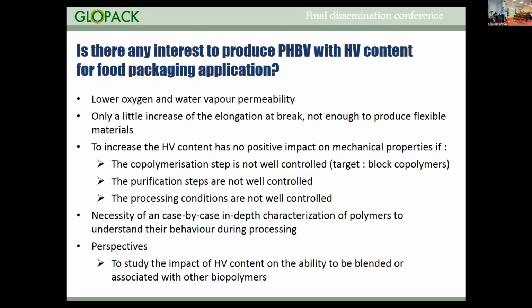The question: is there any interest to produce PHBV with high HV content for food packaging application? The answer is yes, if you consider the lower oxygen and water permeability that is obtained. But regarding the mechanical properties, only a little increase of the elongation at break has been reached, which is not enough to produce flexible films from pure PHBV if it's not blended with other biopolymers. Also, increasing the HV content has no positive impact if the copolymerization step is not well controlled, so we have to target block copolymers. The same applies if the purification steps are not well controlled, and also if the processing conditions are not well controlled. So it is yes, but we have to control a lot of parameters after this bacterial synthesis. We also have to study case by case all the produced PHBV to define these parameters.